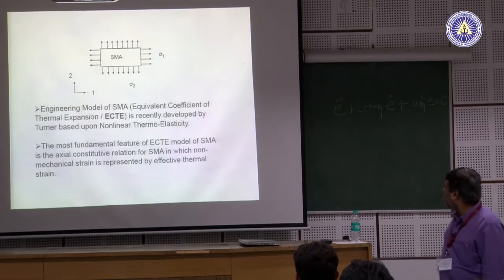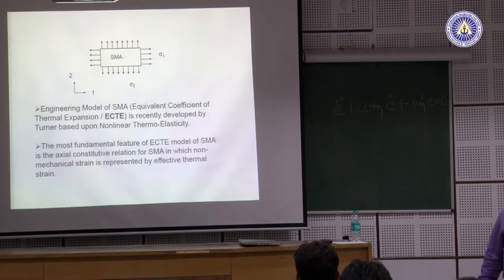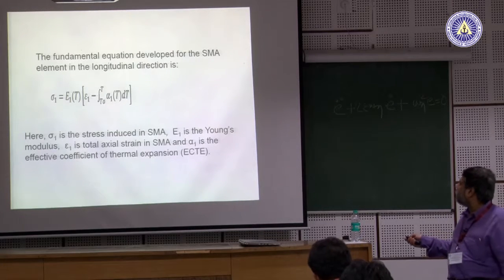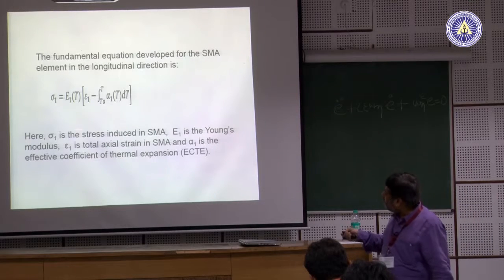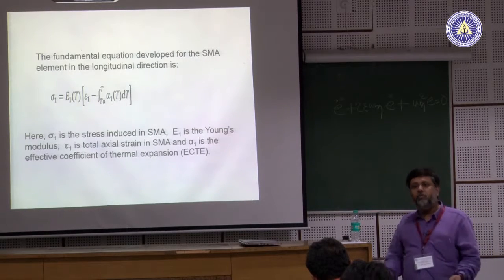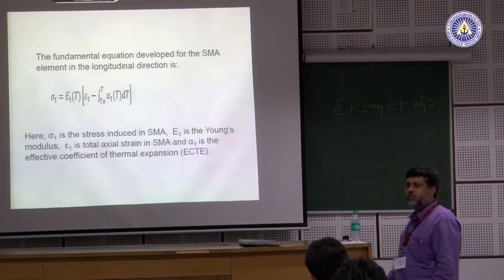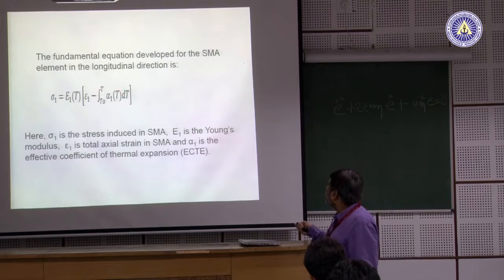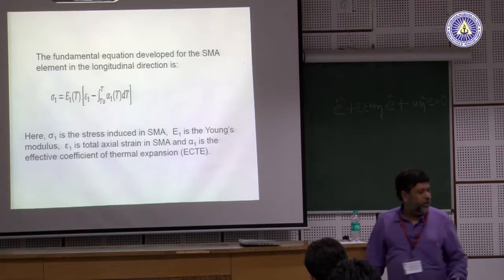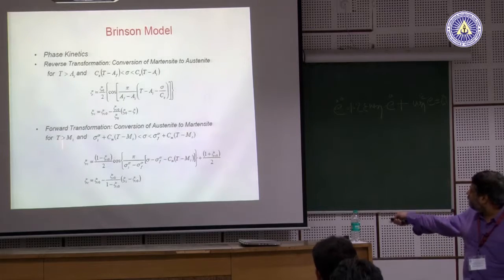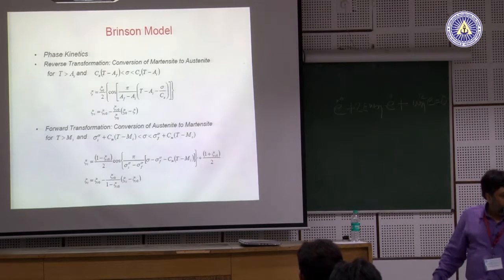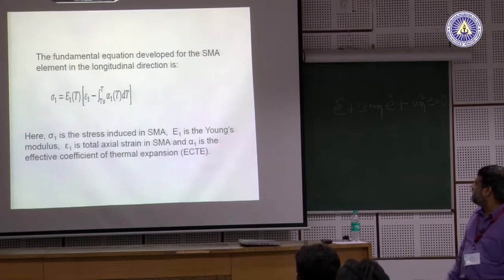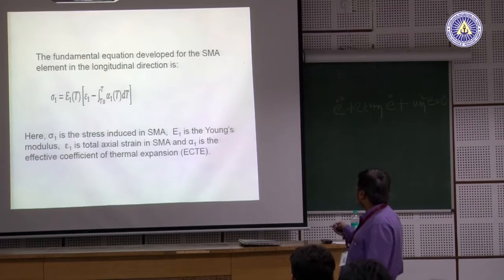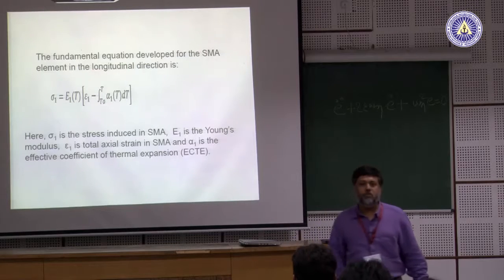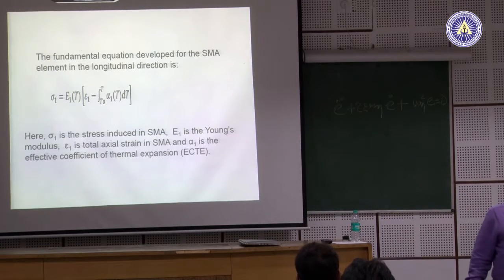thermal expansion model, and it is very simple, like you already know the thermal expansion coefficient of a system. All we have to know is, for the shape memory based system, from the experiments we find out what is the response of the system, and then find out what is the equivalent thermal expansion coefficient which has accommodated this forward and reverse transformation. For both cooling and heating, this alpha changes, and once you know that alpha experimentally, you feed it up, the model becomes simpler. Only thing is that you have to carry out a series of experiments to have this simpler model.